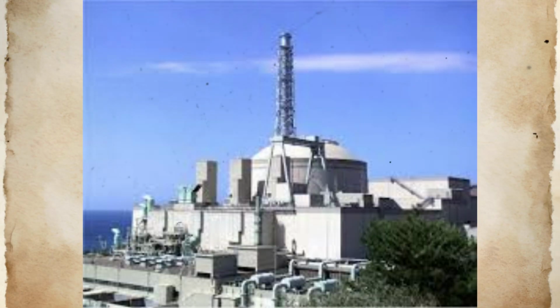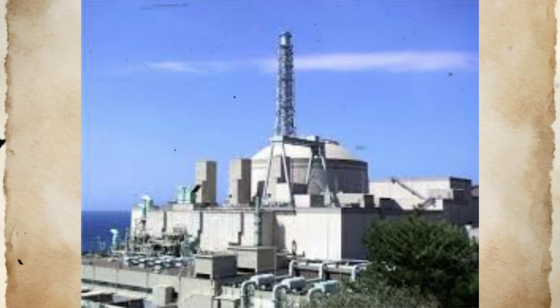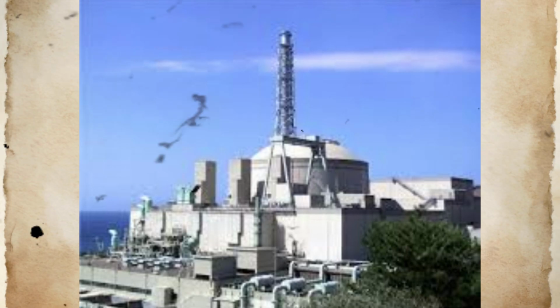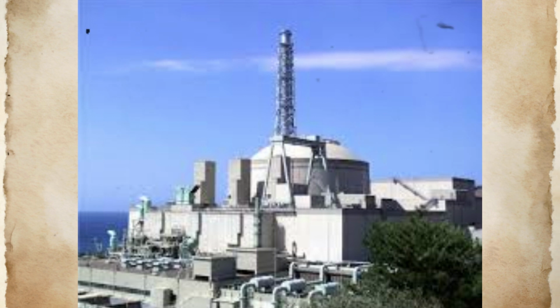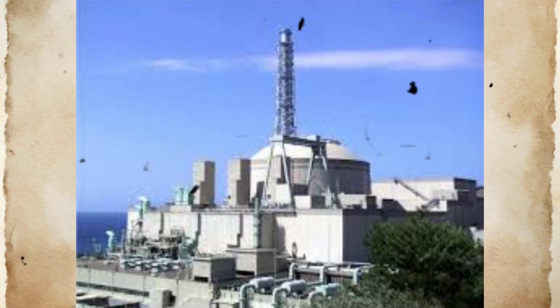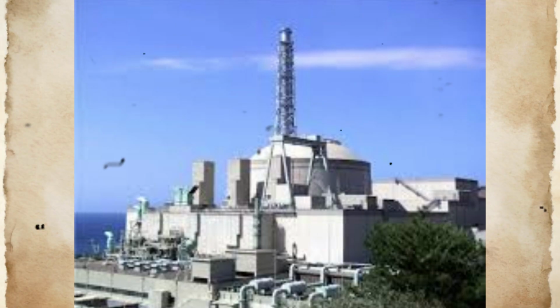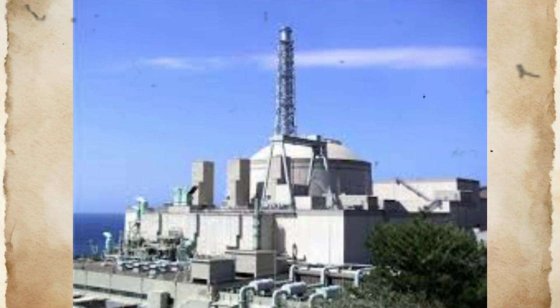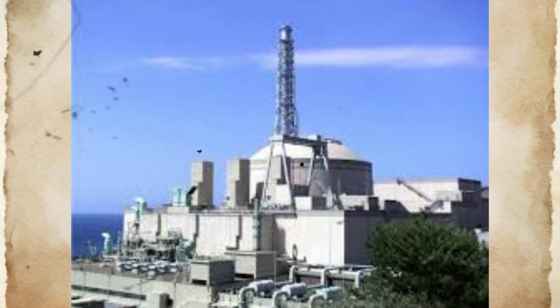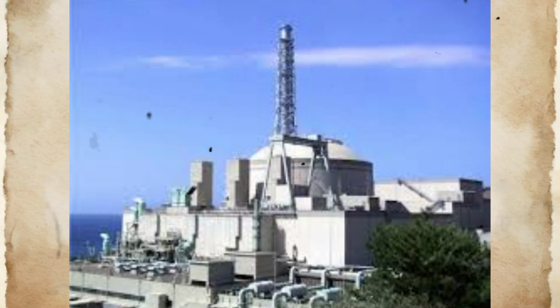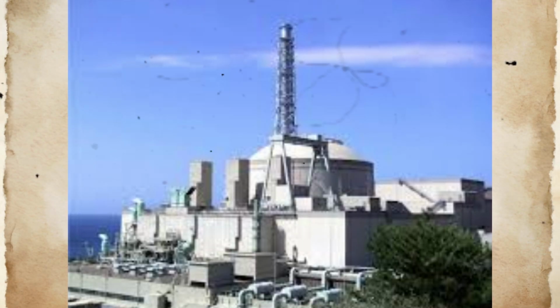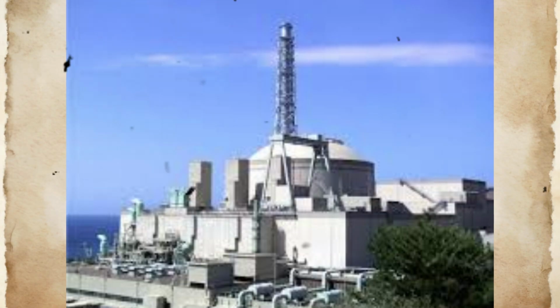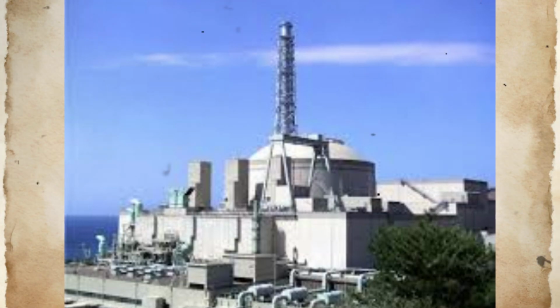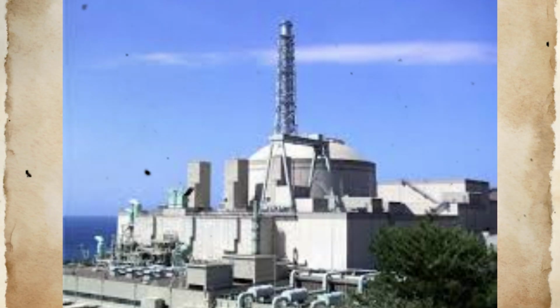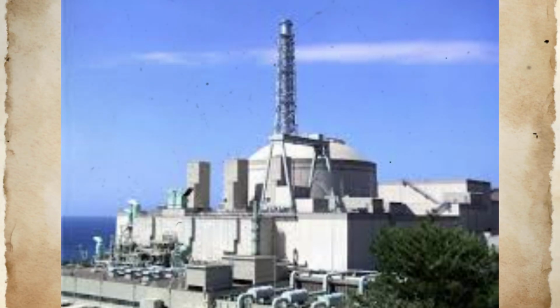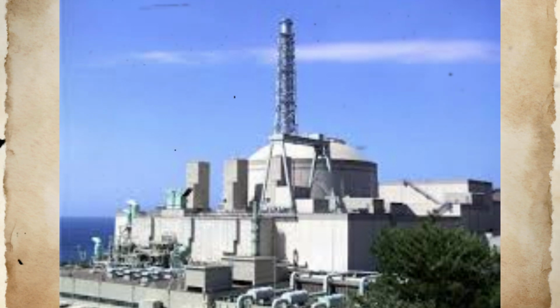The sharp taper geometry used at Monju was intended to optimize thermal response time by positioning the sensing element closer to the pipe wall boundary layer, but this thermal optimization created the flow conditions that led to mechanical failure. The investigation revealed that design guidance available at the time of Monju construction did not adequately address the interaction between thermal performance optimization and mechanical durability under flow-induced vibration conditions. The 1991 Addenda to ASME Boiler and Pressure Vessel Code Section 3 Appendix N, published after Monju design completion, included provisions for vortex-induced vibration prevention that could have prevented this failure.